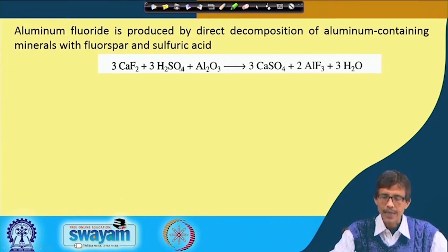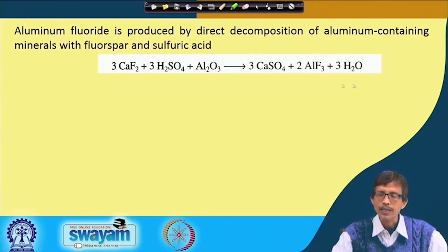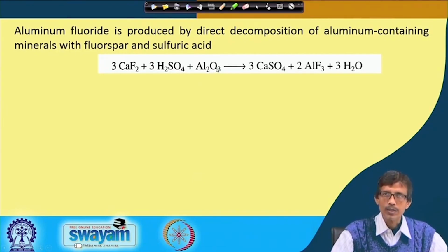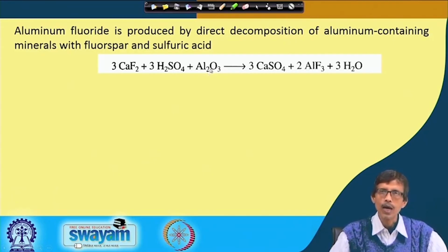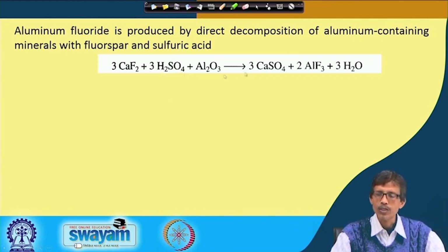So, it is an acid base reaction which will be utilized for the production of AlF3. It is not that a direct reaction of calcium fluoride with alumina will give you aluminum fluoride. You require sulfuric acid, because the 3 oxygen atoms of alumina, per mole of alumina Al2O3, are not utilized for any anion formation, and will be directly taken out as water molecules. So, we use protons, or hydrogen ions, from sulfuric acid as the source, so that 3 sulfuric acid will produce 3 water molecules.